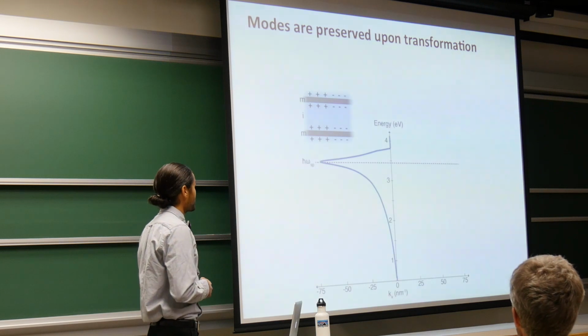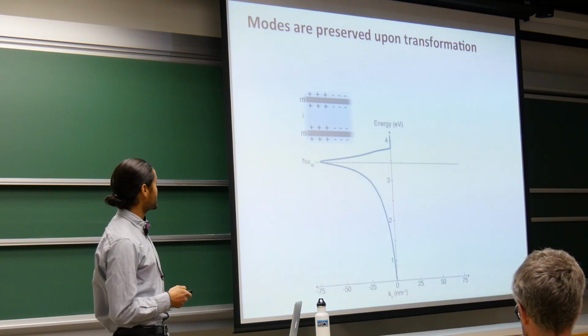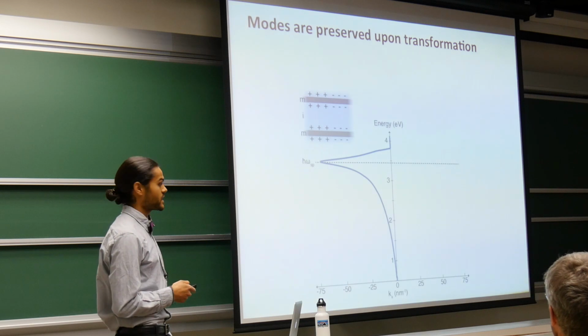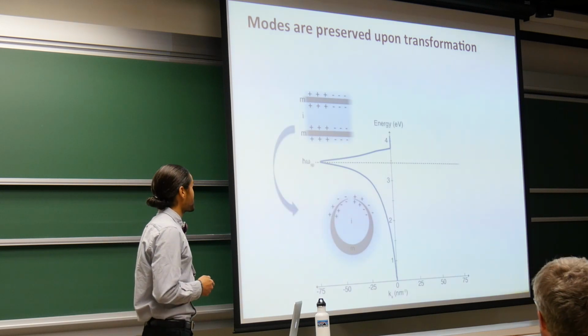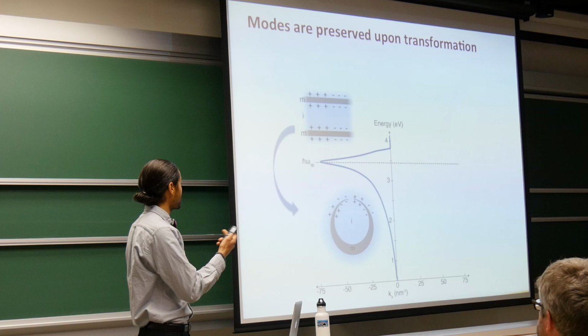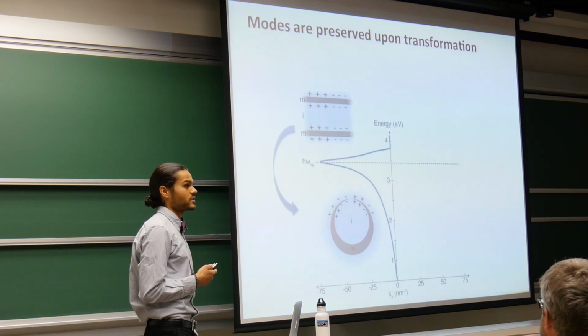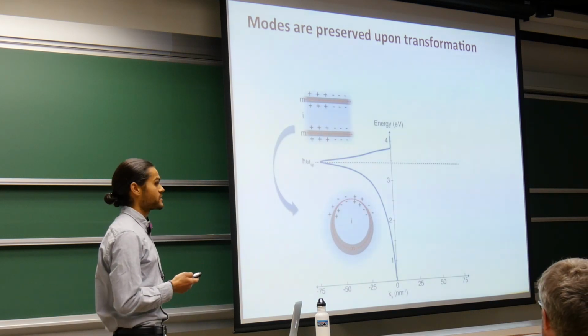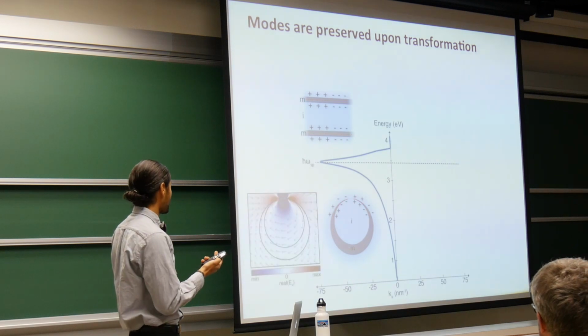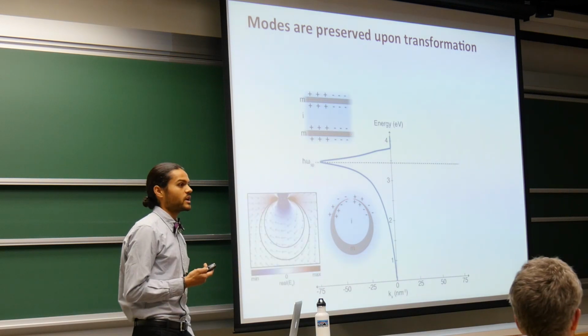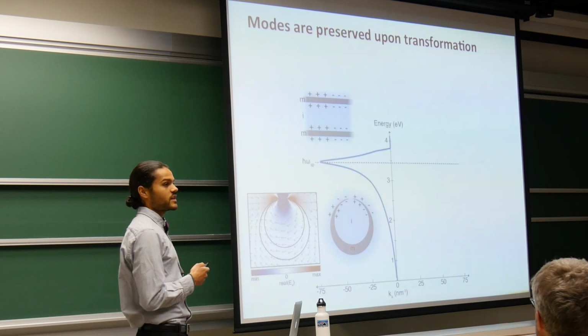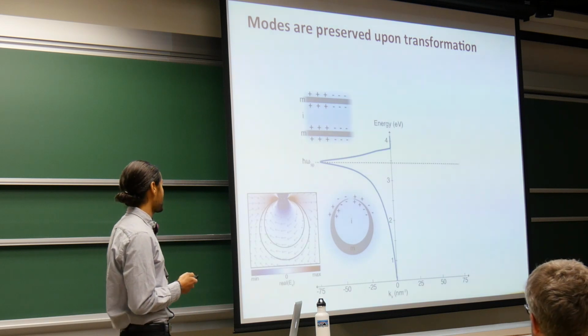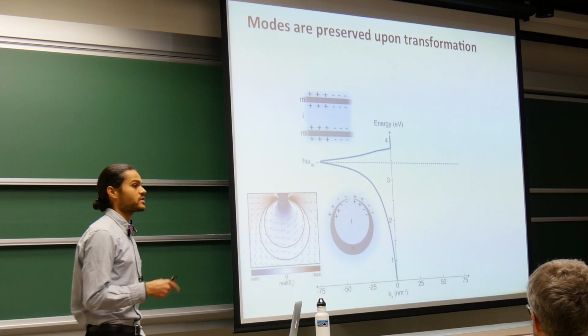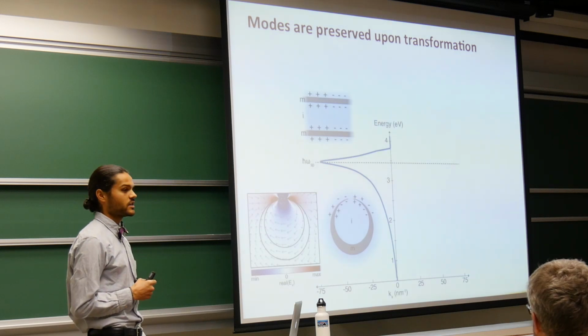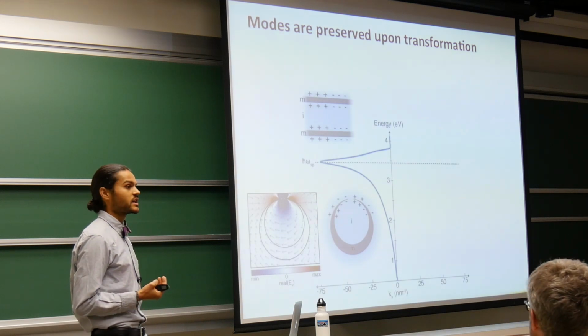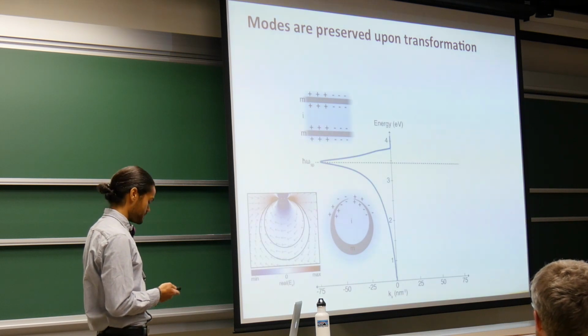So let's find out what happens to these modes upon transformation. Let's first look at the negative index mode. And upon transformation, we can see that the charge symmetry is preserved. So now the charges that were symmetric across the metal layers are now symmetric about a circle of symmetry. And if we look at the charge distribution as well as a near-field plot of this mode, we can see that it is characterized by a very strong electric dipolar resonance near the tips of the structure, as well as a circulating displacement current through the metal shell, which corresponds to a very strong magnetic moment for this particular mode.